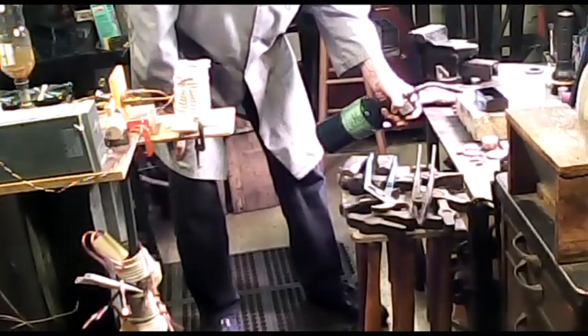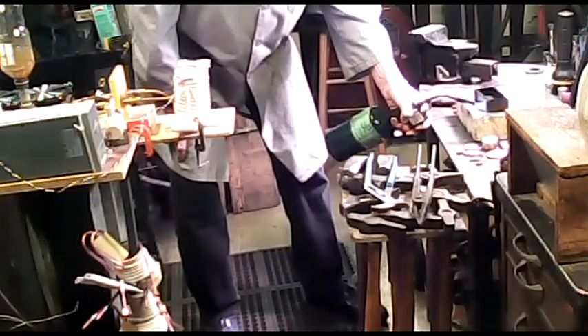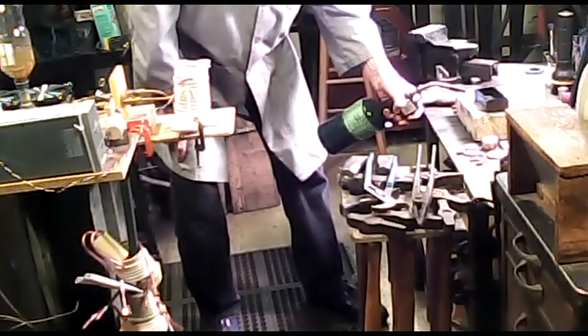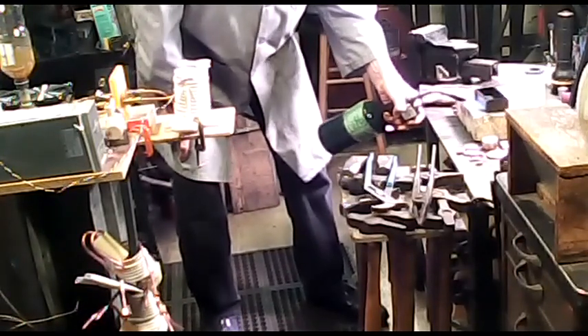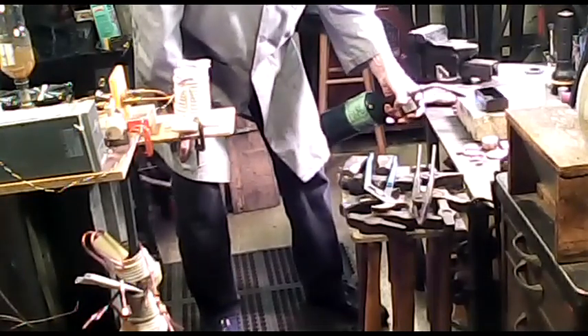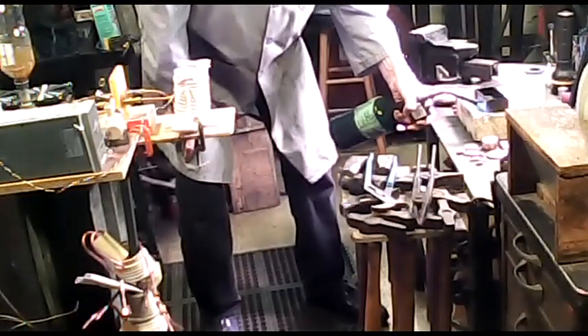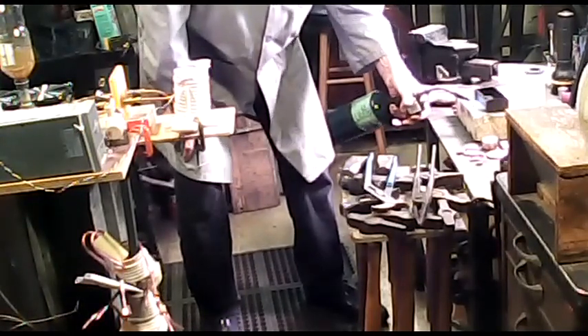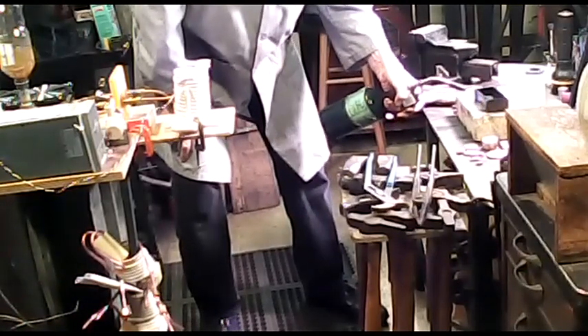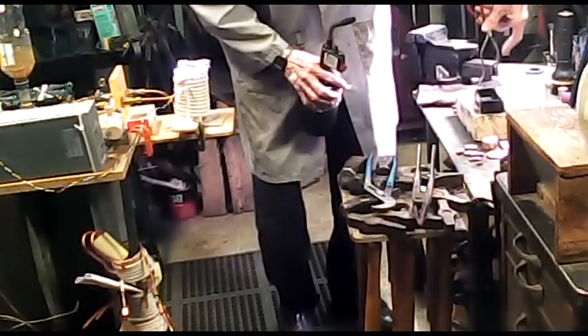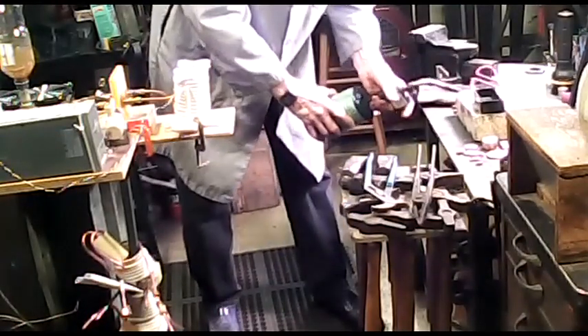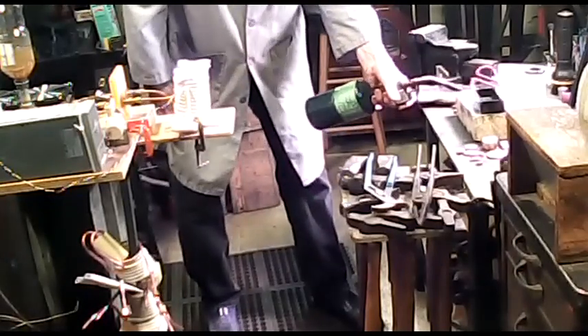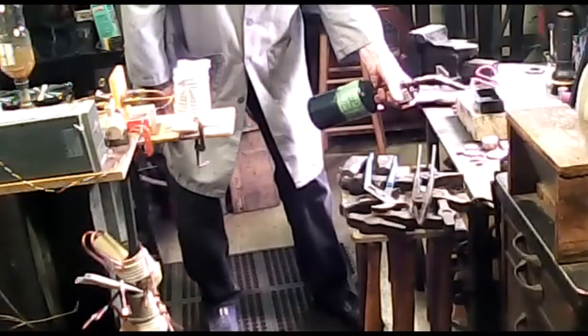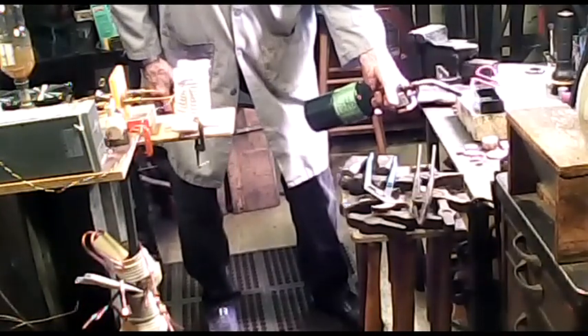All we have to do, or the ingot mold, all we have to do is get the whole thing above the boiling temperature of water, so that we don't have any evaporation occur. We pour that 2,000-degree copper into the mold, and there isn't any water at all. It'll immediately turn to steam and can blow copper all over the place. And as they say, don't ask me how I know. Almost 5 minutes. When it gets to 5 minutes, we'll go ahead and take another set of readings.